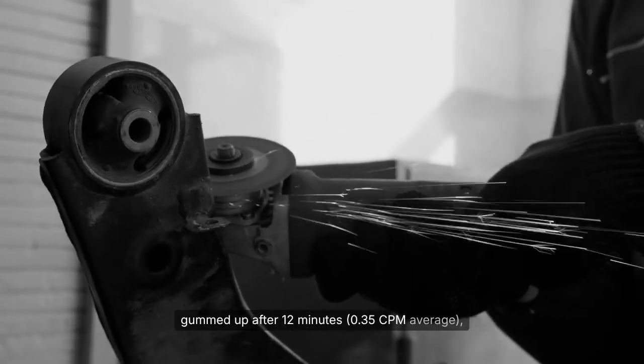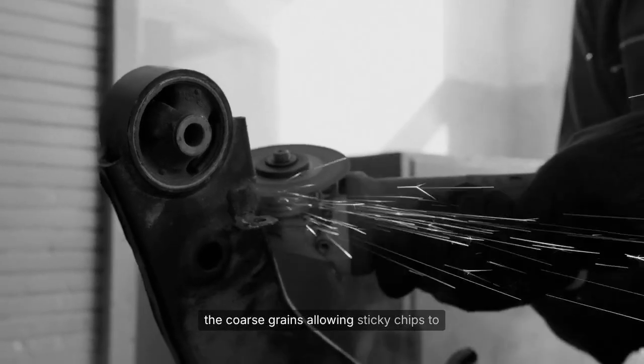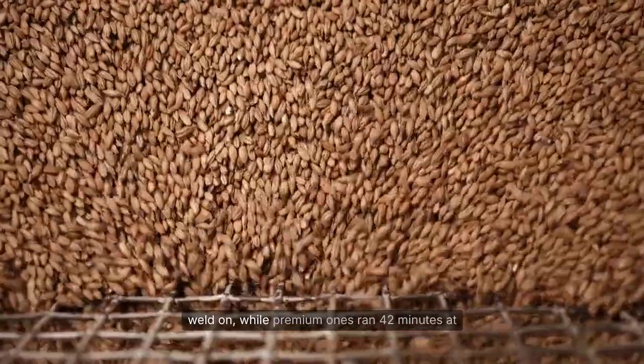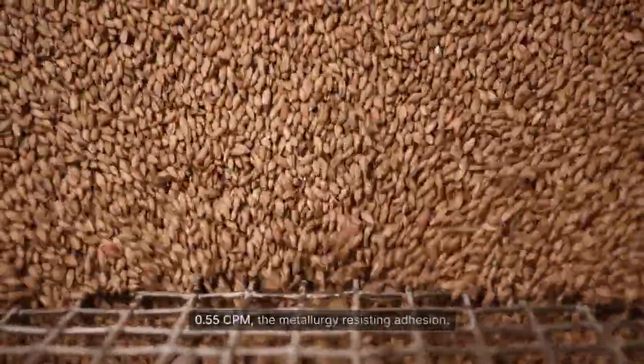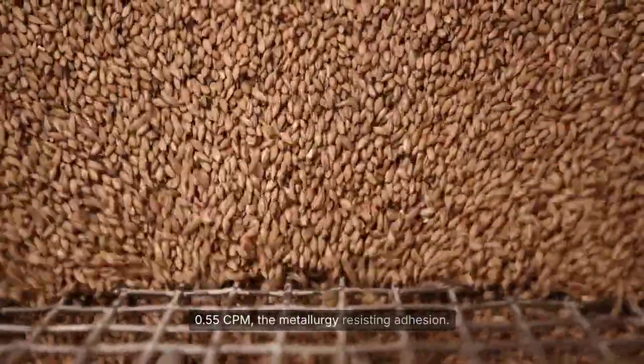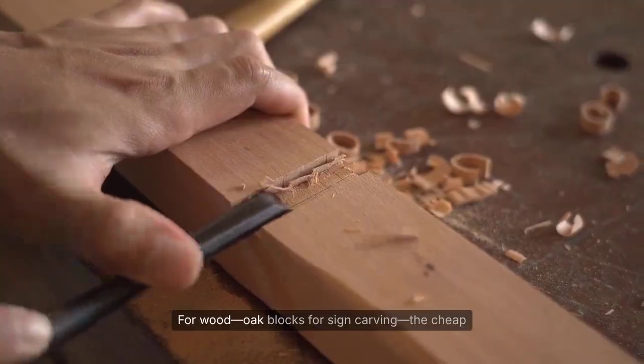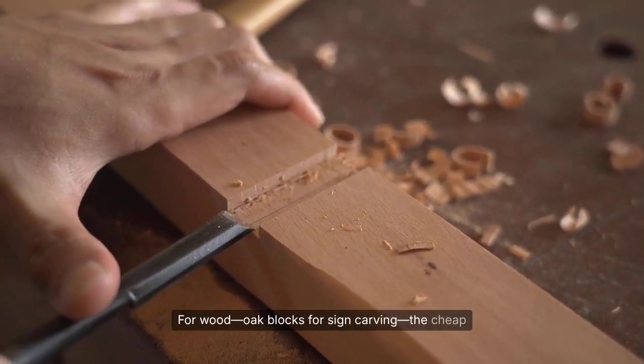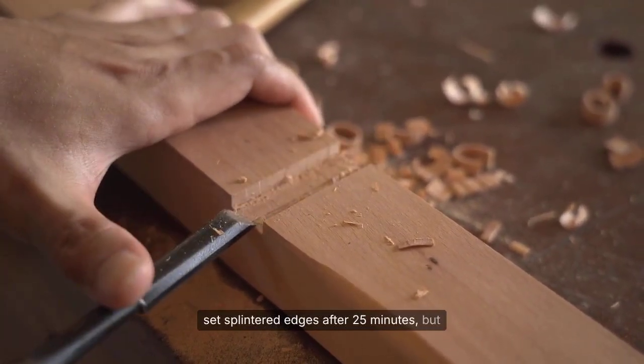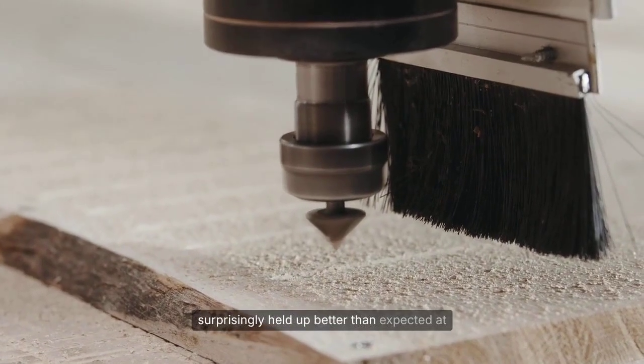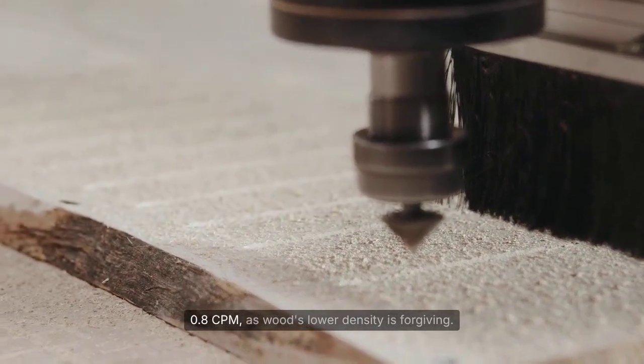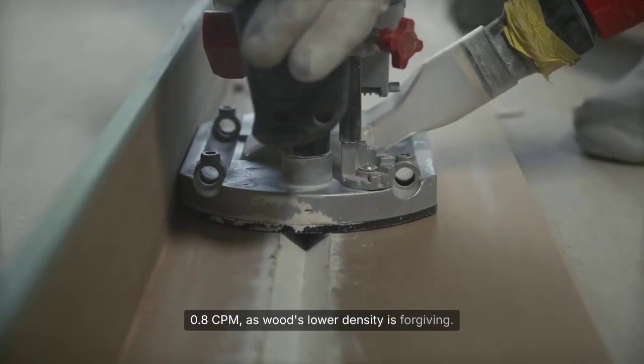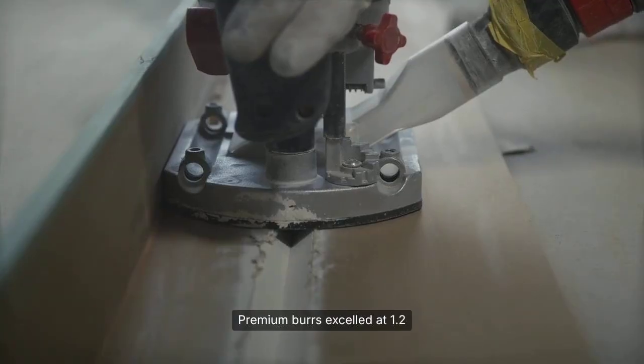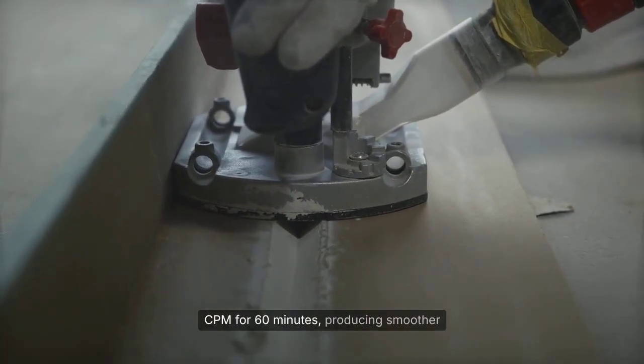Cheap burrs gummed up after 12 minutes, 0.35 CPM average. The coarse grains allowing sticky chips to weld on, while premium ones ran 42 minutes at 0.55 CPM, the metallurgy resisting adhesion. For wood, oak blocks for sign carving. The cheap set splintered edges after 25 minutes, but surprisingly held up better than expected at 0.8 CPM, as wood's lower density is forgiving. Premium burrs excelled at 1.2 CPM for 60 minutes, producing smoother finishes without tear-out.